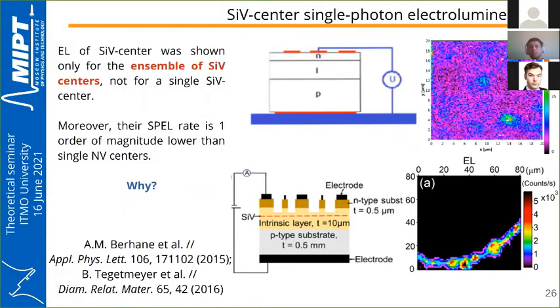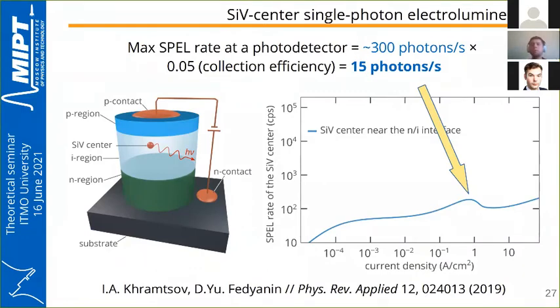Why? Let's look at the dependence of the silicon-vacancy center SPL rate for a center located near the NI interface, as a function of current. The maximum SPL rate will be no more than 300 photons per second, and taking into account collection efficiencies, we obtain only 15 photons per second at the photodetector—impossible to detect given the detectors used in the experiment.